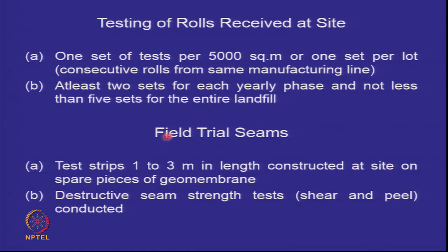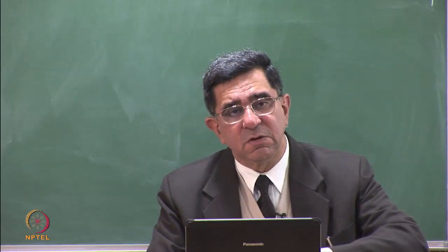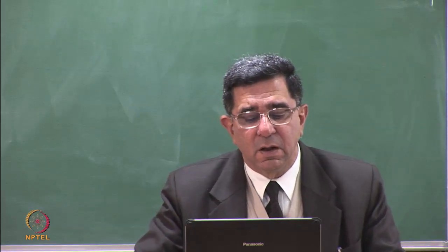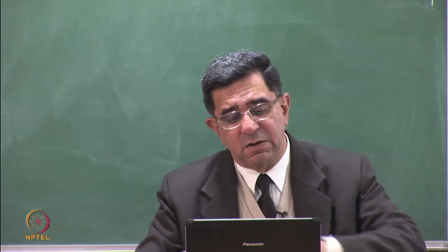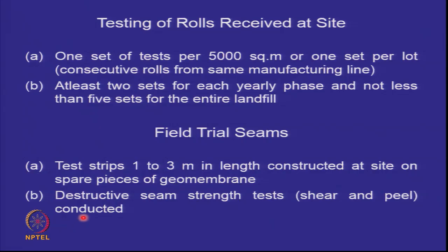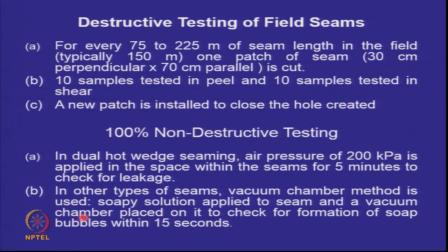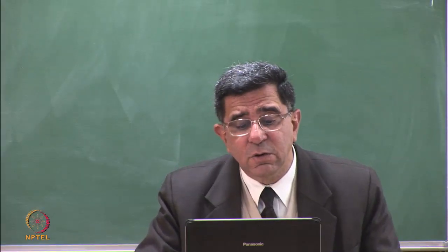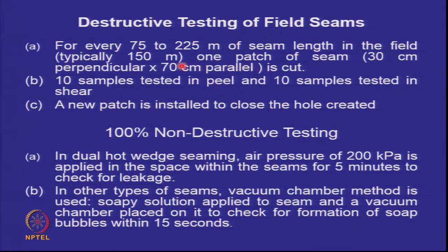Field trial seams: test strips of 1 to 3 meter in length. You will construct these seams or joints on some leftover, spare pieces of geomembrane, and then you will do the shear and peel tests. You will also do destructive testing of field seams. When you have installed the seam, you will cut out portions and do field testing, and a new patch is installed to close the hole which is created.